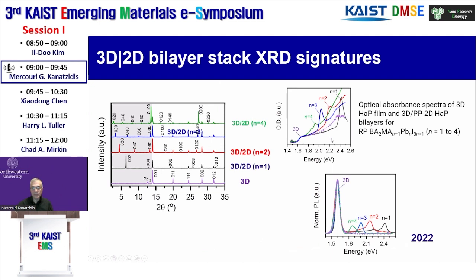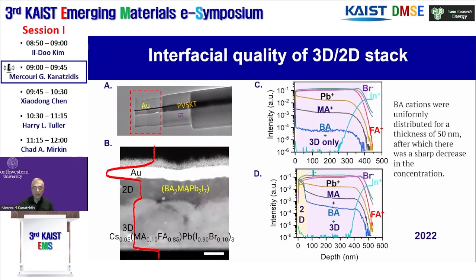For example, you can take absorption spectra, and you can see the absorption of the 3D, and then superimpose the exciton absorptions and so on of the 2D. So here's one film. You see it has N equal 3 on top of 3D. This is N equal 2 on top of 3D, N equal 1, and so on. And so we characterize them thoroughly.